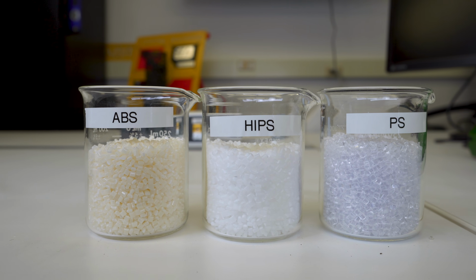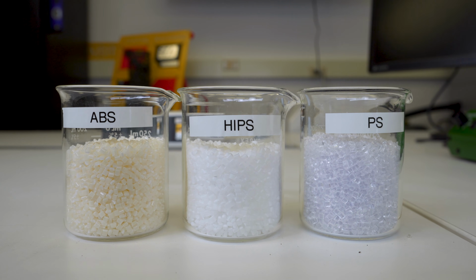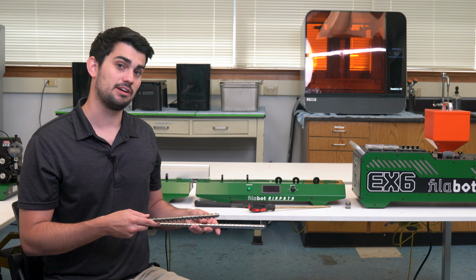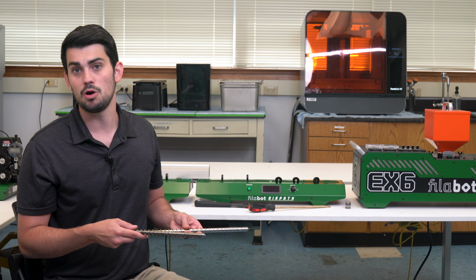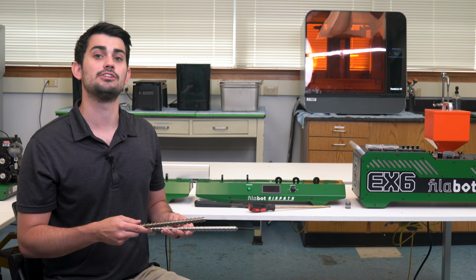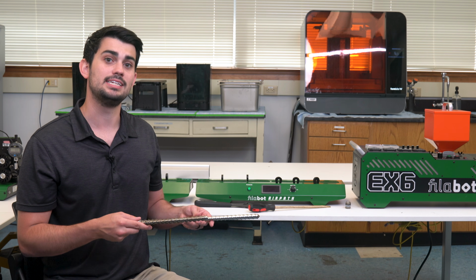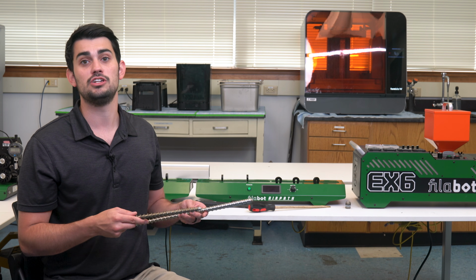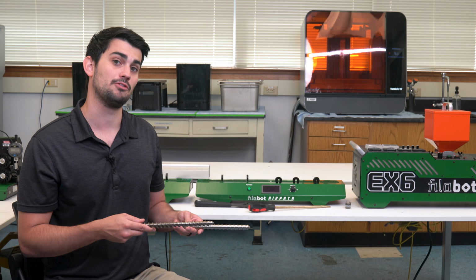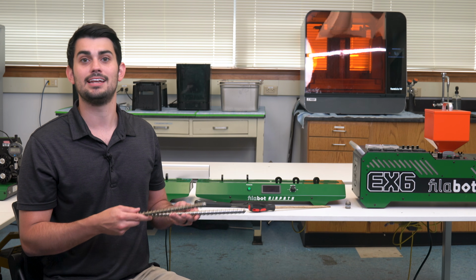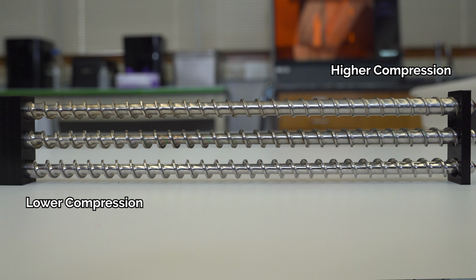But some plastics, especially amorphous ones such as ABS, HIPS, and polystyrene, have a lower melt viscosity and may be sensitive to thermal degradation. Thermal degradation occurs above the plastic's melting point and results in the breakdown of the internal structure of the material. For thermally sensitive materials, the degradation temperature is much closer to the melting point. So care has to be taken not to overheat the plastic melt. A low compression screw can prevent this overheating.